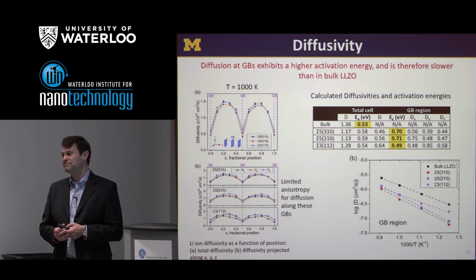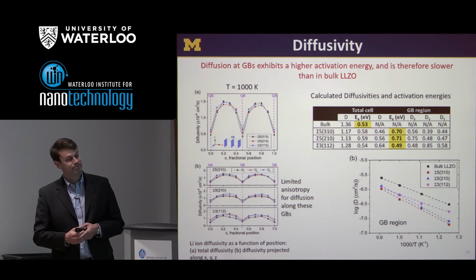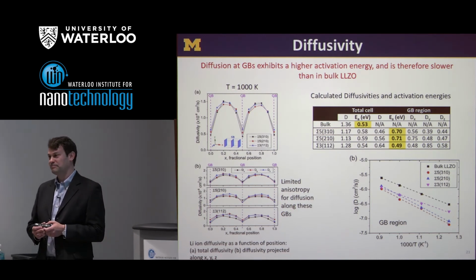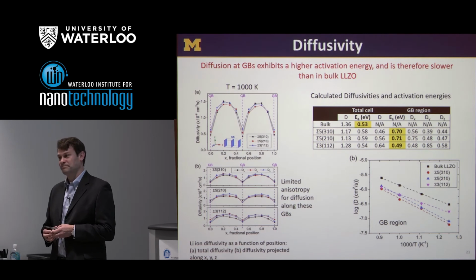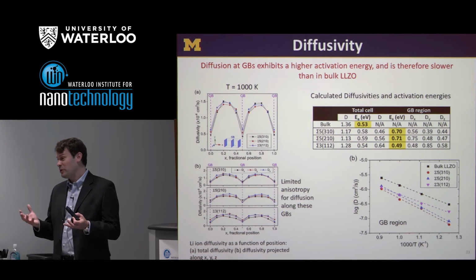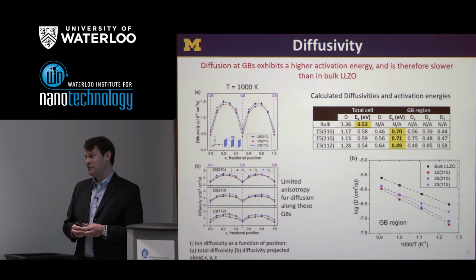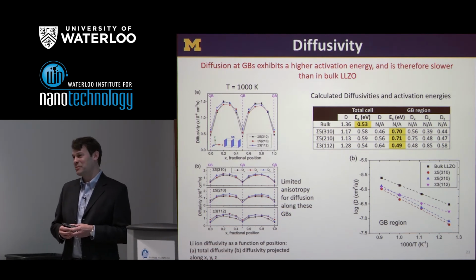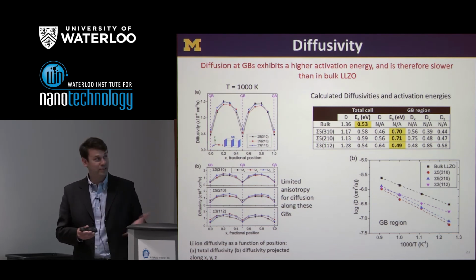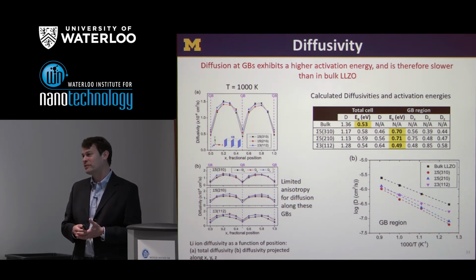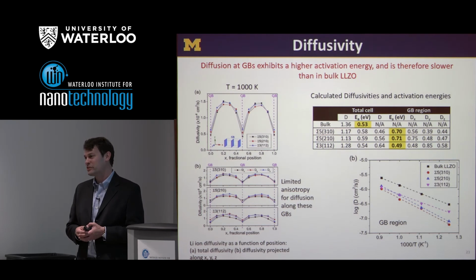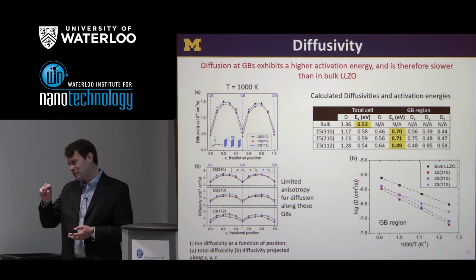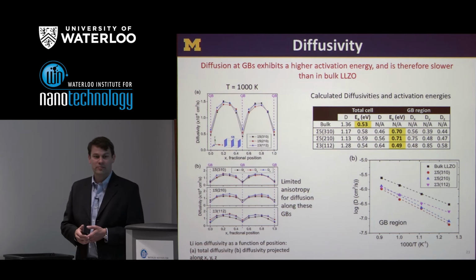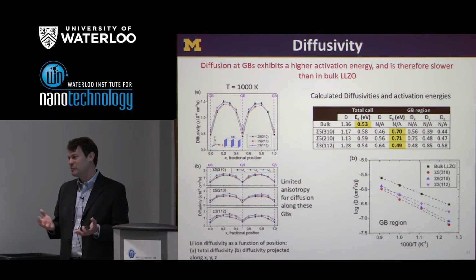So the fact that the lithium is immobile, or fairly mobile in the grain boundary is, I guess, predicted by the calculation. In reality, is this because maybe it is something like Li2O in there? It could be. I mean, we honestly don't know at this stage. Very little is known about what's happening in these grain boundaries, other than people have made some Nyquist plots and tried to back out the grain boundary contribution to the resistance. But chemical accuracy, or a nanoscopic probe of the composition in the grain boundary region, I have not seen published at this point.